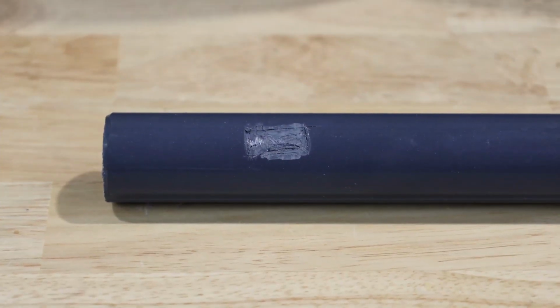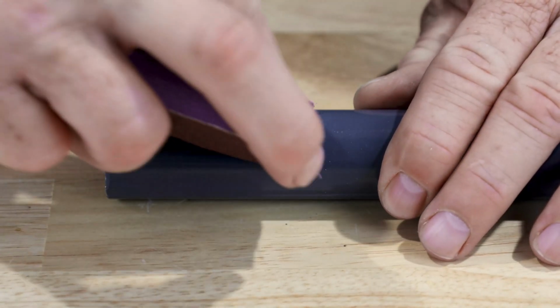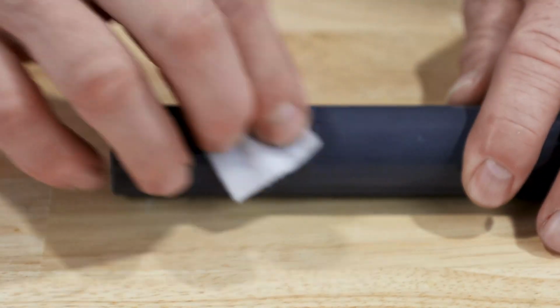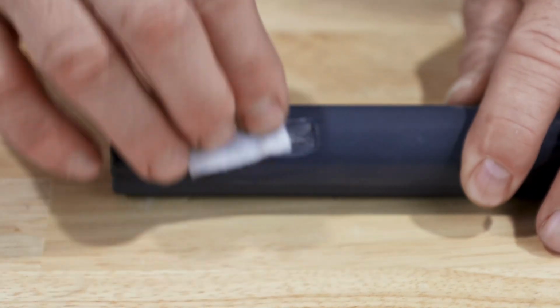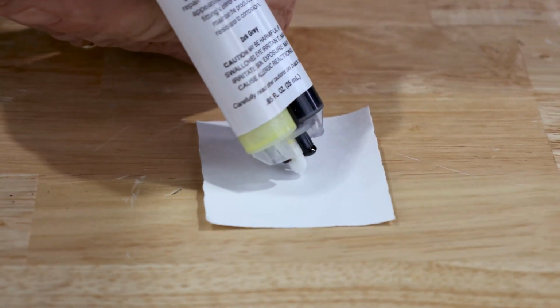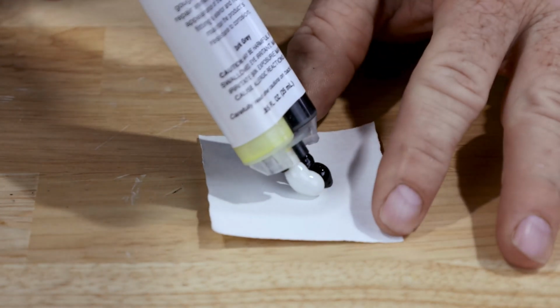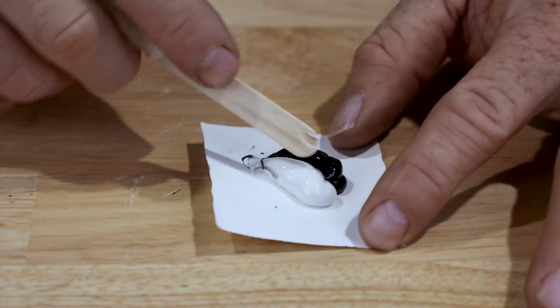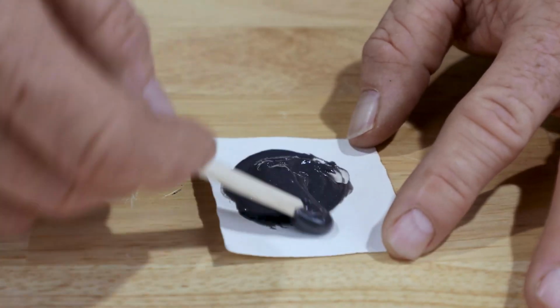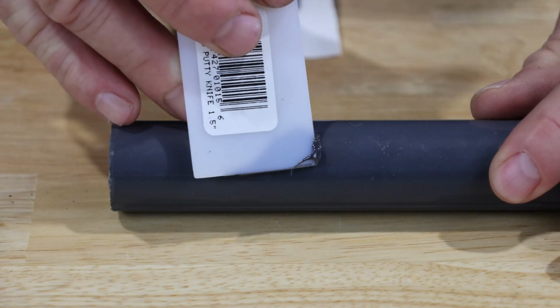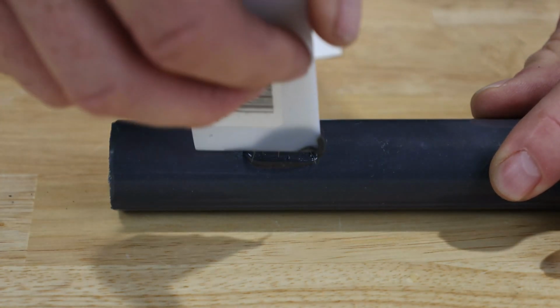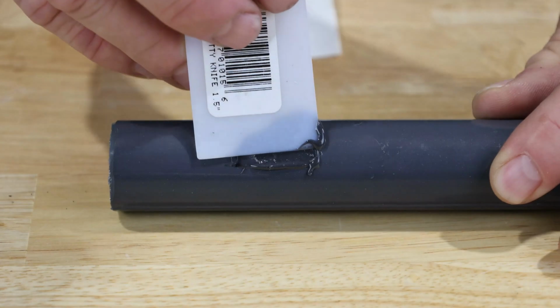To repair the damaged surface of the coating, follow the enclosed instructions. First, use the emery cloth to prepare the surface of the damaged area, removing any debris and creating a good surface profile. Next, use the wet cleaning cloth to remove any excess debris and wipe the area dry with the dry cleaning cloth. Pour equal amounts of the compound from the mixing tube onto the enclosed cardboard mixing surface and use the mixing sticks to mix the compound completely until it is dark gray in color. Once fully mixed, use the enclosed applicator to apply an even coating to the damaged area. The compound will adhere to both the PVC and the metal surface. Several coats may be necessary.